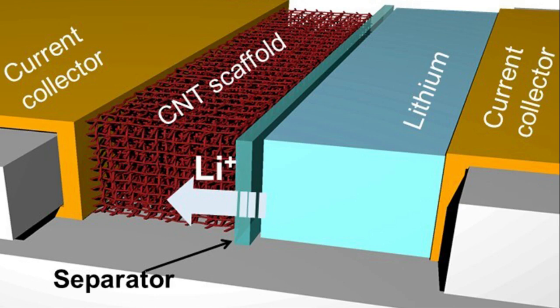Another anode design involves using pure lithium metal instead of graphite. Compared to graphite anodes, those with lithium metal have a much higher energy content per unit mass, or energy density. But they too can fail in the same catastrophic way due to the formation of dendrites. To address this problem, the researchers designed anodes using highly conductive, lightweight materials called carbon nanotubes. These carbon nanotube capsules contain spaces or pores for lithium ions to enter and deposit.